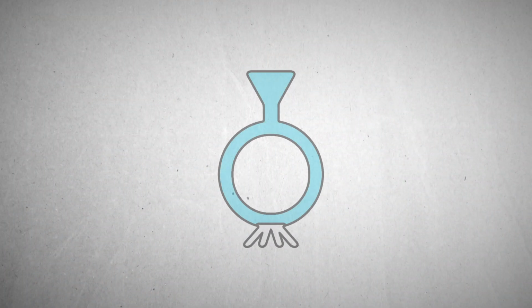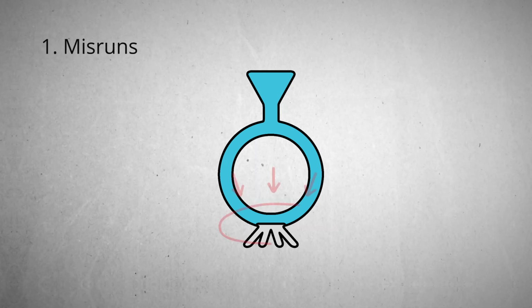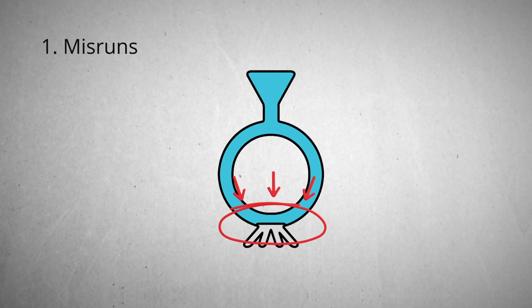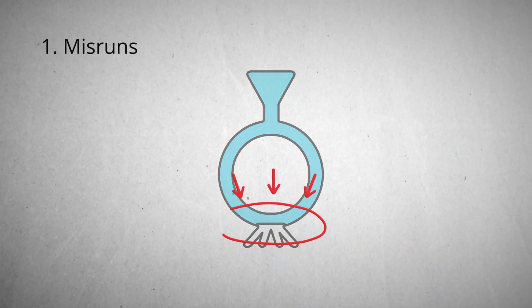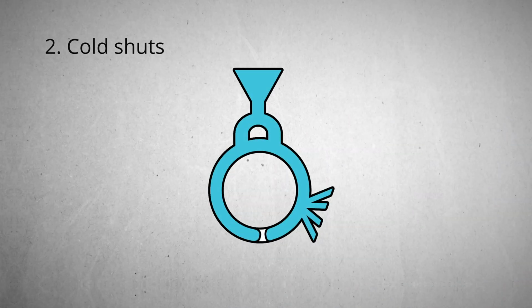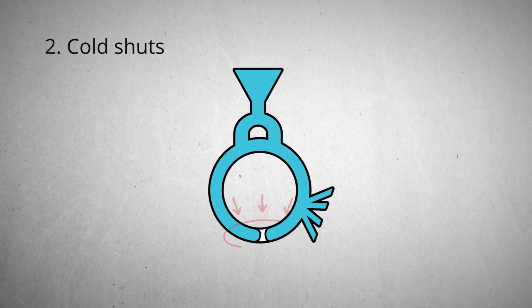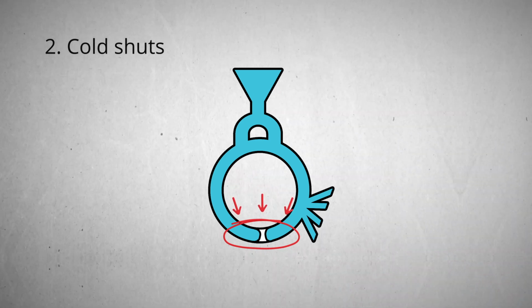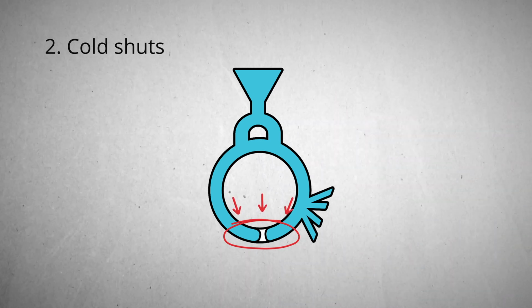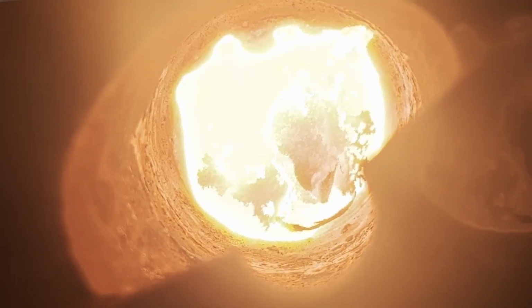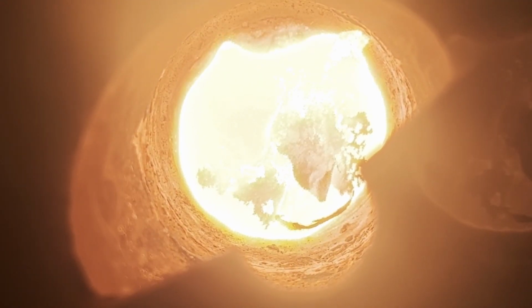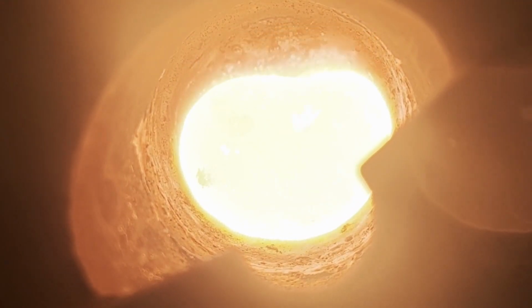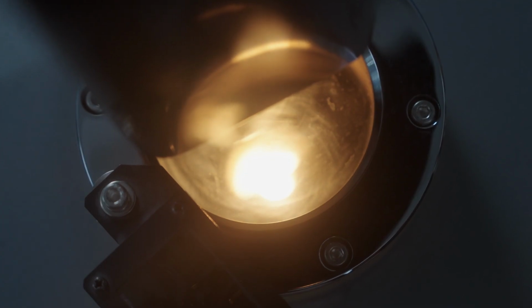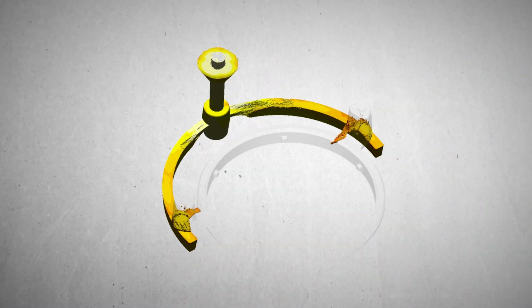A misrun is when the metal solidifies too quickly before it fills the entire mold, resulting in no fill and incomplete parts. A cold shut is when two streams of molten metal meet inside the mold, but have cooled so much that they don't fuse together properly, leaving a line in the casting. How superheat helps is by providing a time buffer to make sure the metal is hot enough, liquid enough, and fluid enough to fill the entire mold, and for separate streams to come together and merge seamlessly.